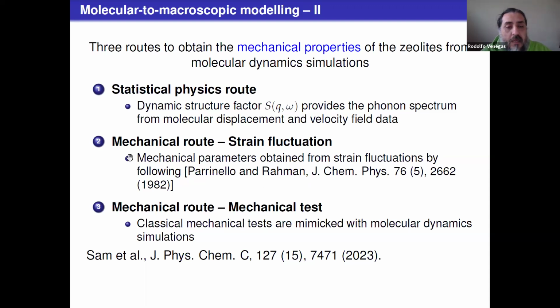Q is the wave number. The second route is the mechanical route, where from the simulations we work out how the strain fluctuates. And from the fluctuation of the strain, we can work out the mechanical parameters following the classical method of Parrinello and Rahman. The third route is a mechanical route too, but a mechanical test. The idea is to mimic what we normally do macroscopically when we test the mechanical properties of materials, like, for example, compression or extension tests or shearing. But we do it with molecular dynamics simulation. That can be considered like a numerical experiment.